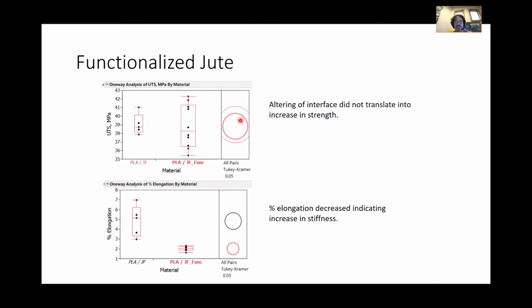What was interesting, though, is that it didn't really have an effect on the yield strength - statistically the same - but it did remove the plasticizing effect that the jute fiber was having. So we maintained the level of stiffness. This may bear further study, but we were able to detect some difference in the mechanical properties by altering the interface, however it didn't manifest in terms of yield strength. So things don't always manifest in terms of yield strength, which is another point of what I'm talking about today.